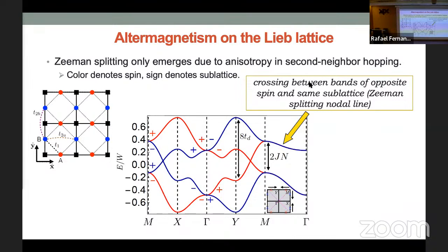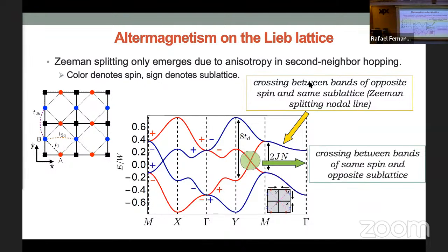But then you notice, and by the way, this is a spin splitting. That's what I mentioned earlier. It's proportional to the hopping, so that's why it's large. Now, what we notice is that there are some additional crossings here. These are crossings between bands of the same spin, but the plus and minus here are just different sublattices. So I have crossings now, and this is not a line, this is a node, so we call this a Dirac crossing, a Dirac point, between same spin but different sublattices.